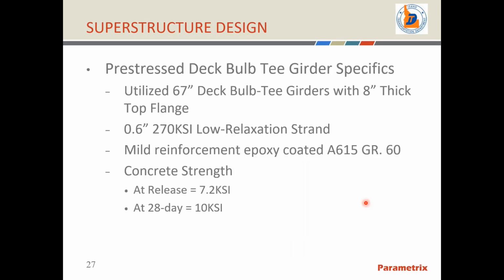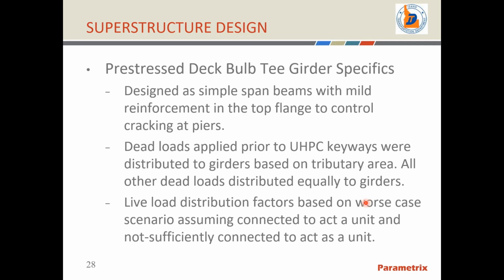More specific about the prestressed deck bulb T-girder design, we utilized 67-inch deep deck bulb T-girders with an 8-inch thick top flange. It used 0.6-inch, 270 KSI low relaxation strand. All other reinforcement was A615 Grade 60, and the concrete at release was 7.2 KSI, and at 28 days 10 KSI. The girders were designed as simple span beams with mild reinforcement in the top flange to control cracking at the piers. Dead loads were applied prior to the UHPC keyways as distributed based on tributary area to the girders. So basically anything that would be non-composite on a conventional composite deck girder system went tributary to the girders.